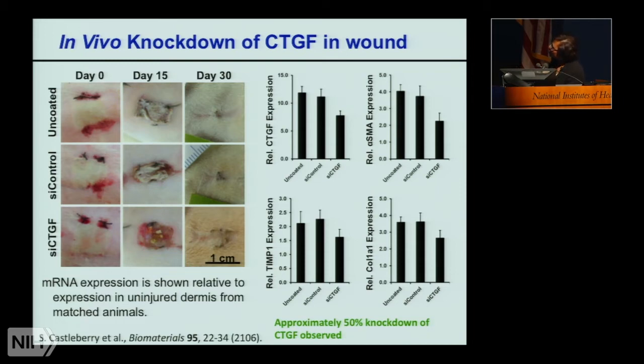This is a third-degree burn model that is carried out at the Shriners Burn Center at Mass General Hospital with Martin Yarmush. In this burn model, you can suture the edges of the burn and then watch to see whether or not the burn contracts. If this tissue contracts the way it shows here, this contractile wound healing is part of the fibrotic response. In our system, you can see that with just a control, we get the same kind of shrinkage of the wound. But with the knockdown of CTGF in these cases, we can see that there is a real reduction in this kind of contraction.